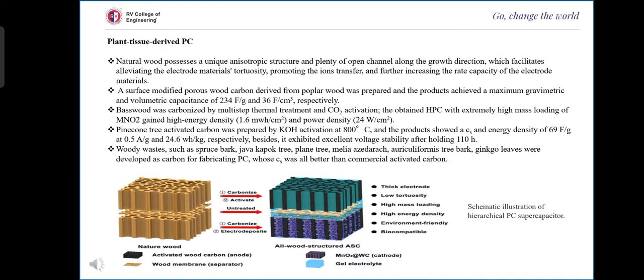The third one is plant tissue-derived porous carbon. Natural wood possesses a unique anisotropic structure and plenty of open channels along the growth direction, which facilitates lowering the electrode material tortuosity, promoting ion transfer and further increasing the rate capacity of the electrode material. A surface-modified porous wood carbon material from poplar wood was prepared, and the product achieved a maximum gravimetric and volumetric capacity of 234 F per g and 36 F per centimeter cubed, respectively.